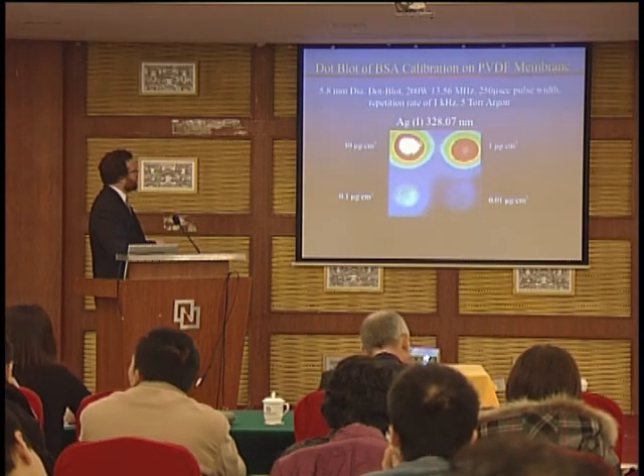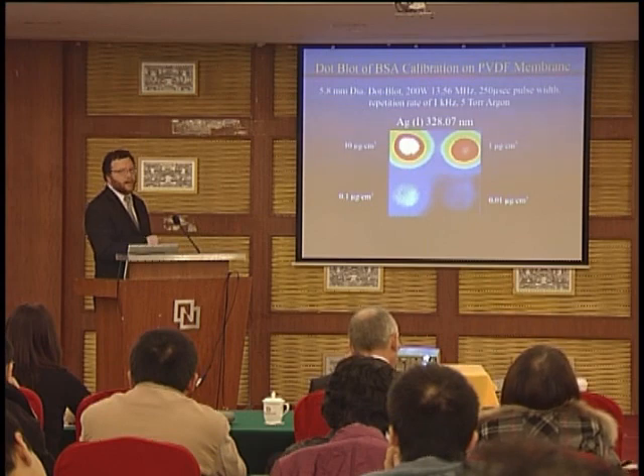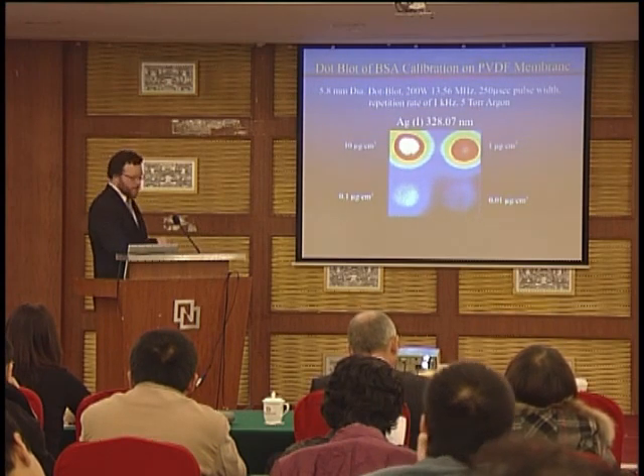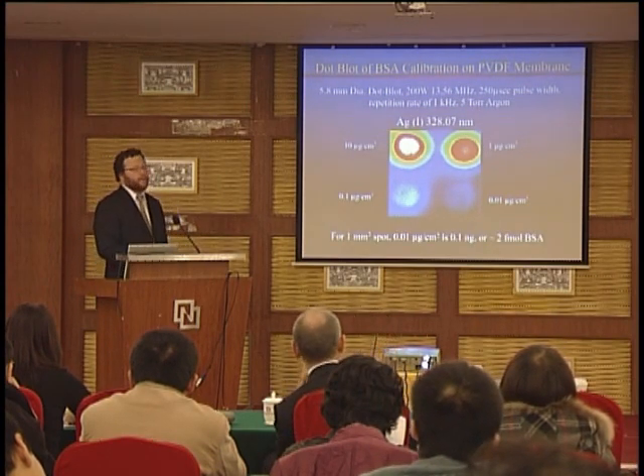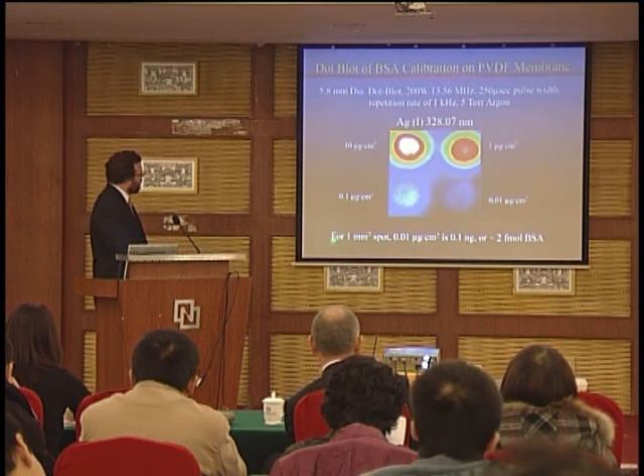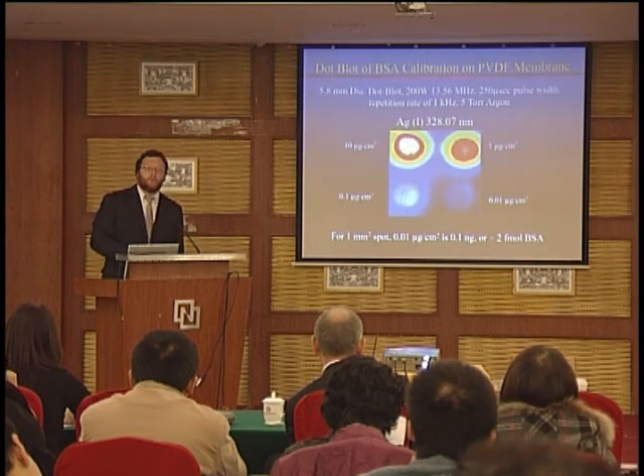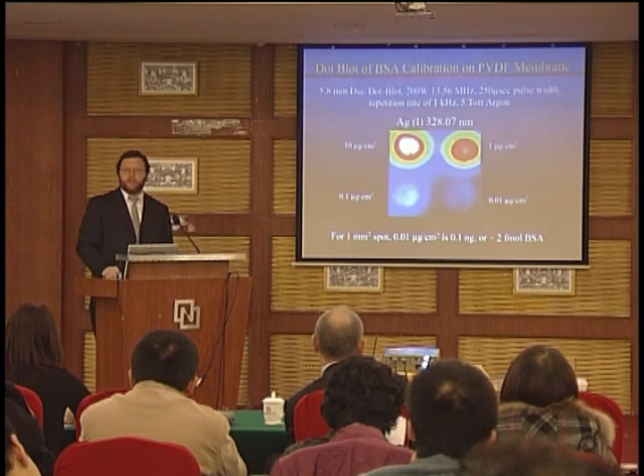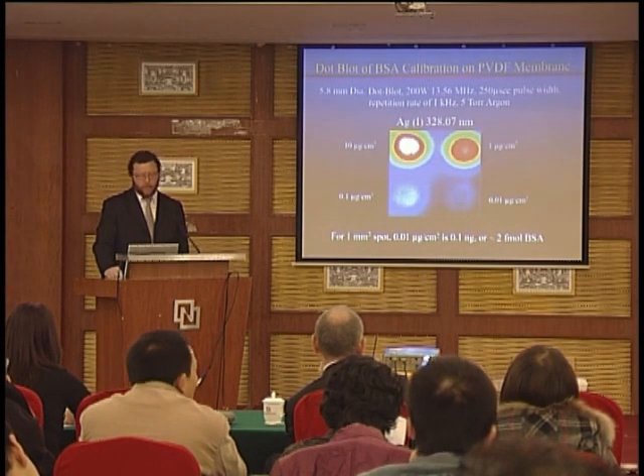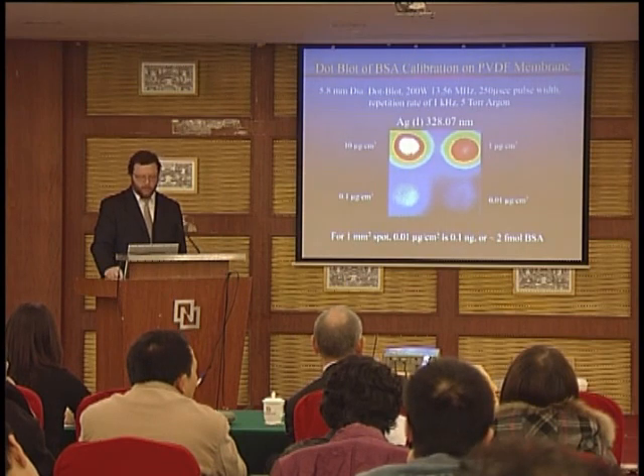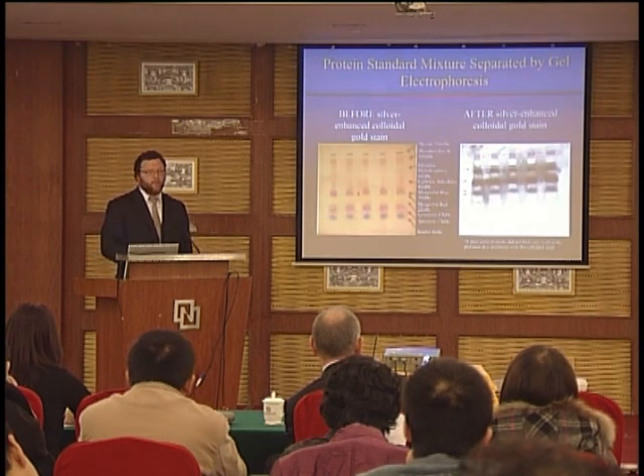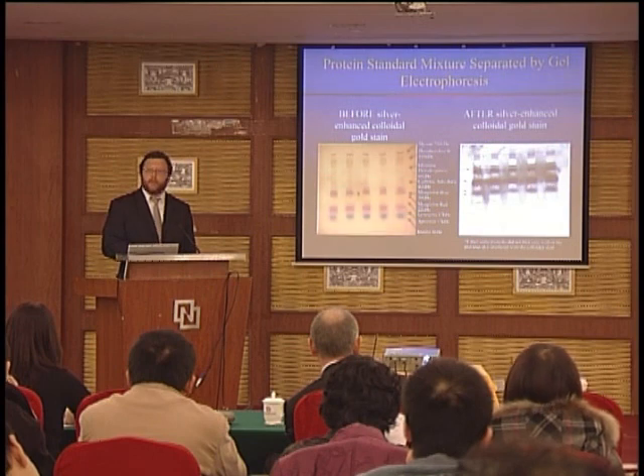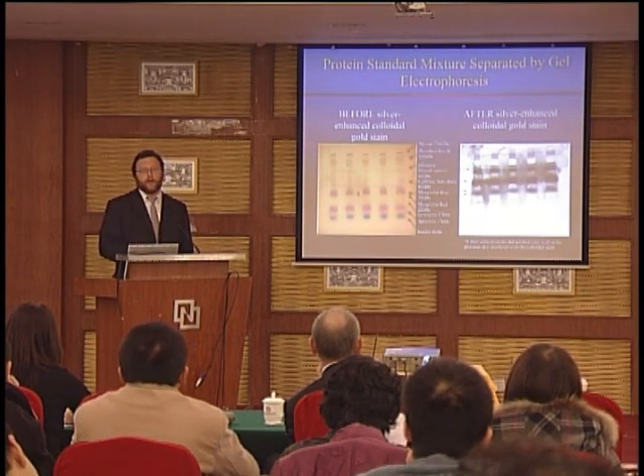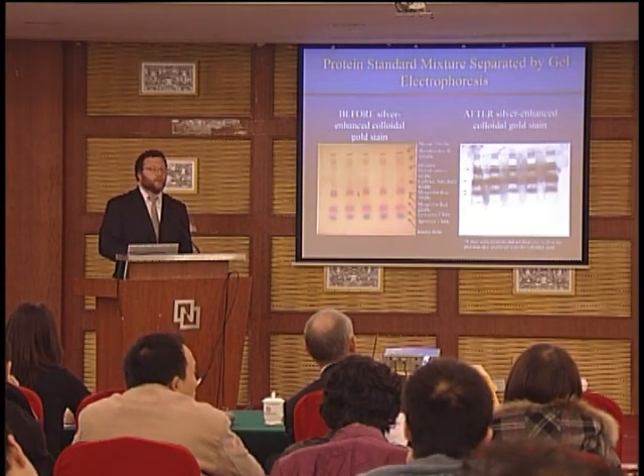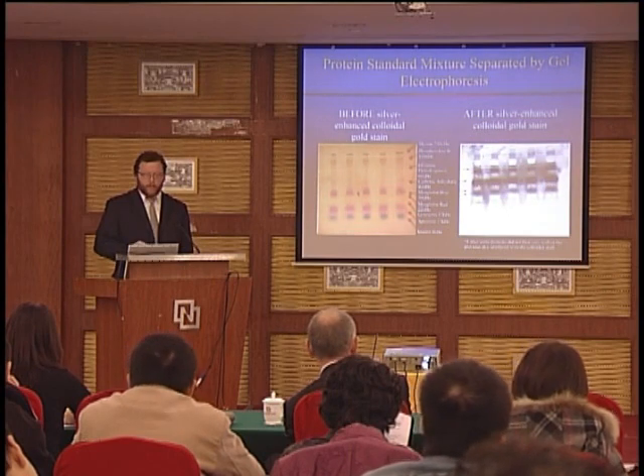What you see here is that you see higher emission, of course, at the higher protein concentration. Here at the lowest concentration, if you do a quick back of the envelope type of calculation, for a 1 square millimeter spot, you'd get a limit of detection of about 2 femtomoles of BSA, which actually is fairly good for a fairly simple method. We'll compare that here in just a moment. Here is a standard protein mixture that was separated now in a one-dimensional gel electrophoretograph, and we blotted it using the mechanism that I talked about before, and we imaged it.